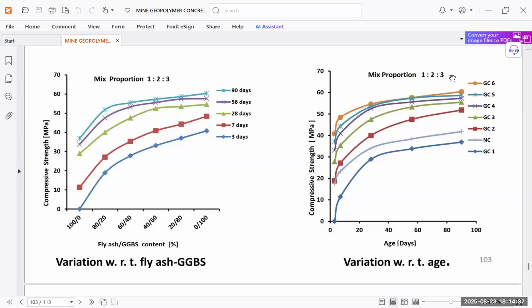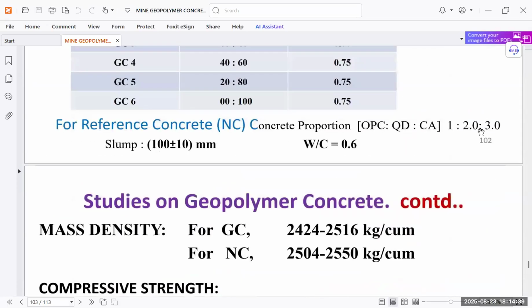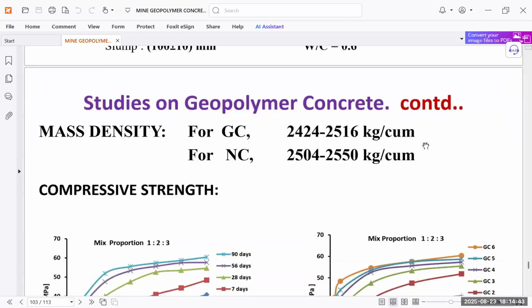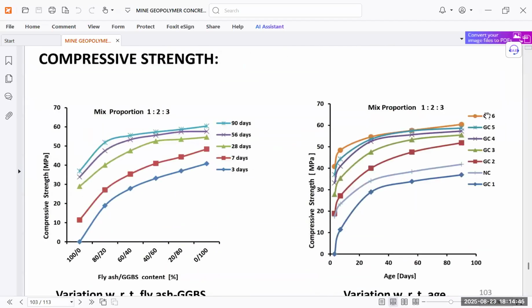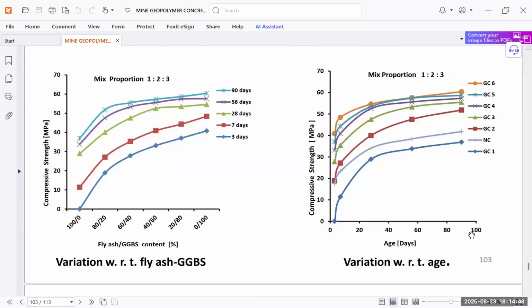The mix proportions are ratio 1, ratio 2, ratio 3. This is the mix proportion with OPC to CA ratio for the normal concrete also here. So we can see these ratios, and we can get the required strength with age also. We are getting the required results by comparing with the normal concrete also. We can get the result as per the requirement of the work.